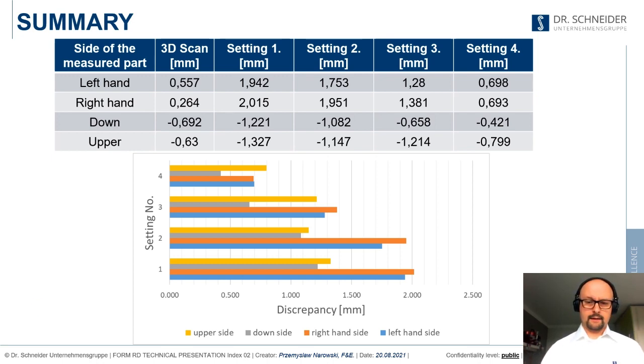You can also see that the discrepancy is getting larger in the areas which are more distant from the gate, which corresponds somehow to the pressure gradient, because the part is injected from the left to right, and we can see that on the right hand side the deviation of the simulated and measured values is larger. So probably we are right with our assumption that the pressure and the pressure gradient in our cavity has really the largest influence on the final result of the displacement after the annealing.